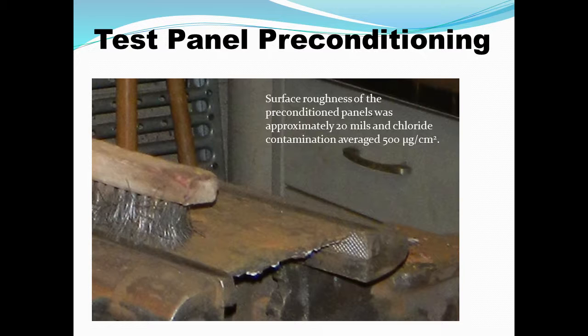The average chloride content on these after SP2 cleaning was 500 micrograms per square centimeter of salt. That sounds like a lot, but we've actually measured 450 micrograms per square centimeter of salt on bottom flanges of bridge beams late in the winter, early spring, before it's been flushed off a lot. So de-icing work can put a lot of salt in your system.